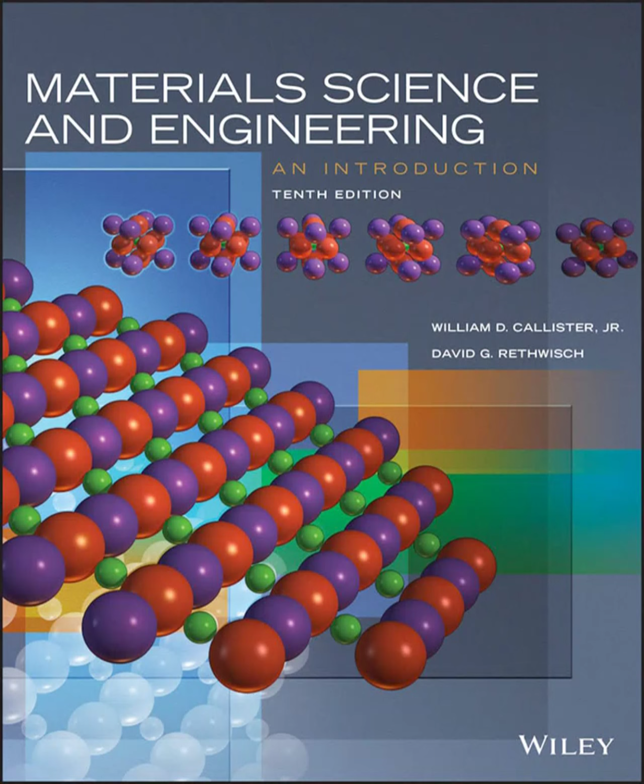And does it match reality? Remarkably well, usually. For example, if we calculate the theoretical density for FCC copper using its known atomic radius and weight, the calculated value is extremely close to the density you'd measure in a lab. It's about 8.89 g/cm³ calculated versus 8.94 measured. That's impressive agreement. It really shows this atomic model works. It does. It highlights the predictive power of understanding these crystal structures.